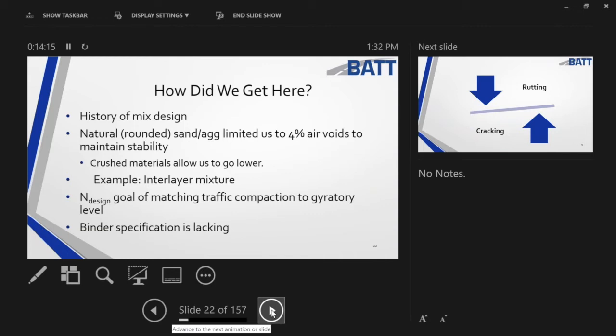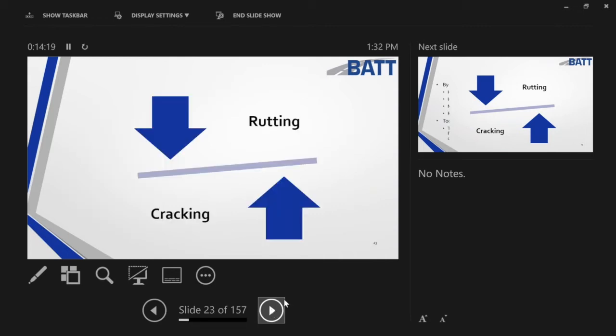Again, binder specification, as we've seen, is lacking. What I mean is that there's no test in there that helps us to understand adhesion, and the fatigue parameter, what they call the PAV DSR test, is good for unmodified materials, but not really helping us for where we're at today. So again, in basic form, it comes down to a balance between rutting and cracking.